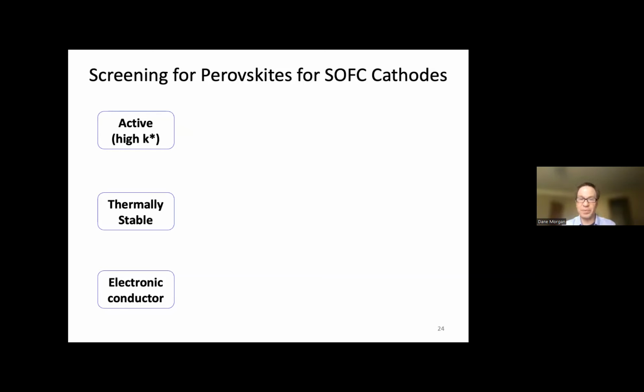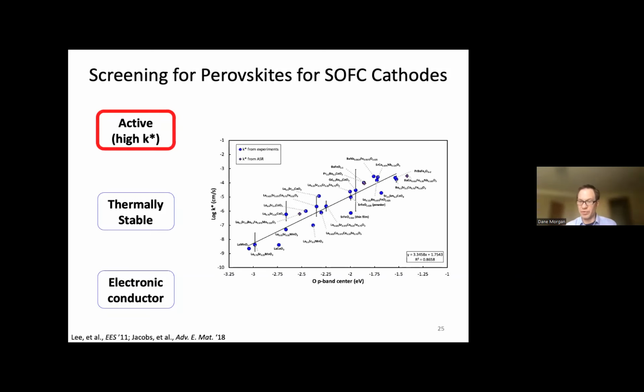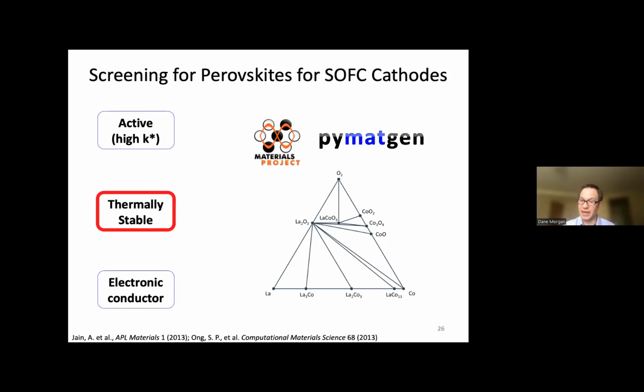So how do we explore whether they have a high surface exchange coefficient? Well, we have this wonderful correlation between the p-band center, which is easy to calculate, and the log of the surface exchange coefficient. So we're just going to use this correlation, and then we're going to calculate a lot of p-band centers. How are we going to decide if they're thermodynamically stable?